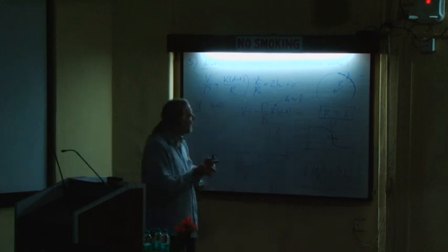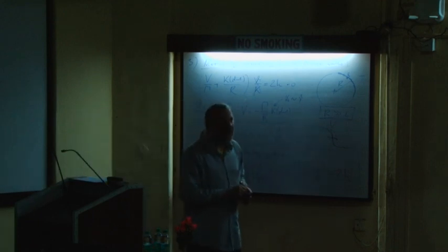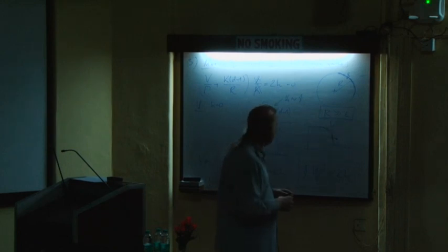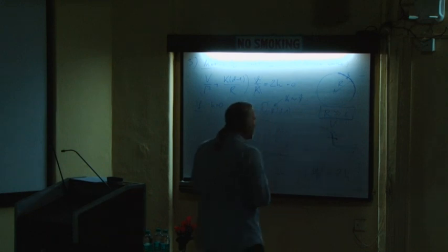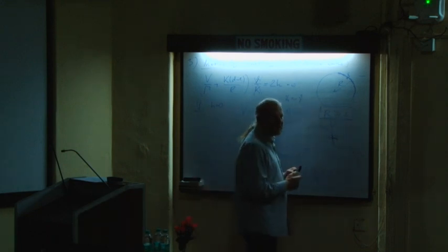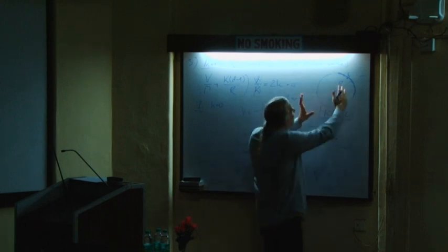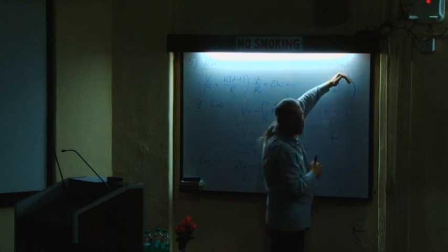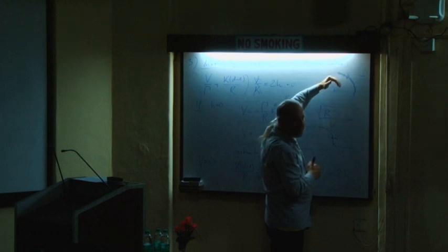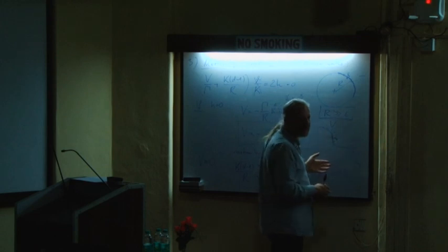Now, why this relation is important, it will show up in plenty of other contexts. This, in some sense, is a variant of what is called the Gibbs-Thomson effect. This time, we have a free energy difference between the two phases. Okay? That means if the droplet wants to shrink, it could reduce its surface area, but it would need to replace the favorable phase with the unfavorable phase. So there is a balance between surface and bulk energies.